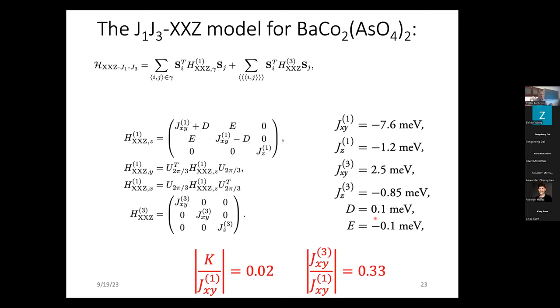Just want to point out, I have to be careful with my time. I want to point out that the ratio of the third near neighbor easy plane interaction to the first near neighbor interaction turns out to be 0.33. And a little bit later in the talk, this will turn out to be an interesting result because it places the material very close to a critical point and possibly a critical phase.